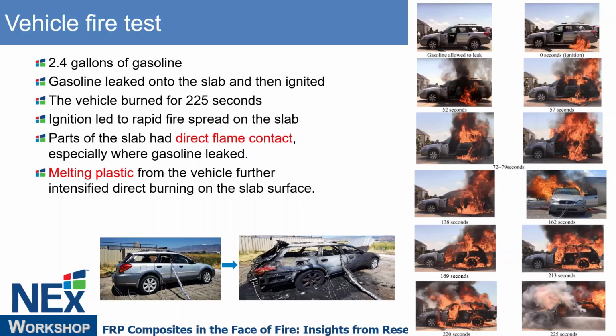In the test, at the beginning, we left 2.4 gallons of gasoline in the gasoline tank in the vehicle, and then we let the gasoline leak onto the slab and then ignited it. It's basically to replicate the vehicle corrosion leading to gasoline leaking from the tank, which then leads to the burning of the vehicle, which is very common in real vehicle scenarios. And the vehicle fire burned for 225 seconds, and it was stopped earlier than we expected because there was a jet flame from the gasoline tank.